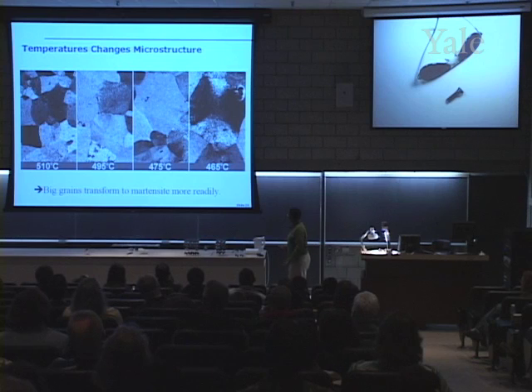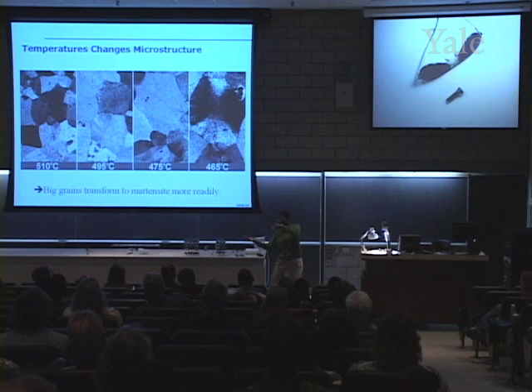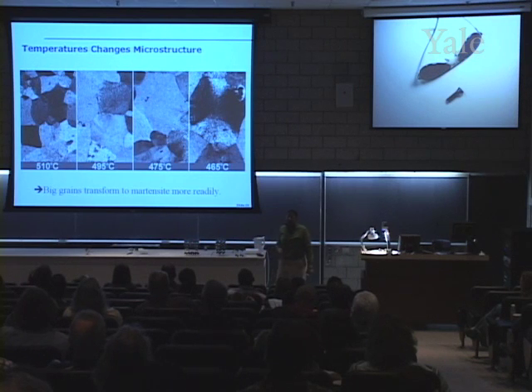Now, what's interesting is that at lower temperatures, we have very large grains. Did you see this big grain right here? You see that? That's a grain. And over here, we have smaller grains. Do you see that? Now, what's interesting is that these grains have lines in them. Those lines indicate martensite. Remember that monoclinic structure that's kind of floating around, the one that kind of looked shifted? That indicates martensite right there. So these big grains have quite a bit of martensite. However, these smaller grains at the higher temperature, they don't seem to have as much martensite.